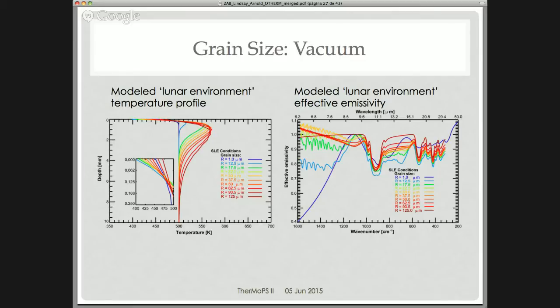So for the smaller grain sizes, you see this, but then in the intermediate sizes, it shifts and narrows. But then for the much larger grain sizes, it's doing what you'd expect. At first I thought this might be an issue with our normalization, but it's really hard to see on this plot, it's also happening, and maybe you can see it, in the secondary CF. So that's something we need to explore a little bit more.